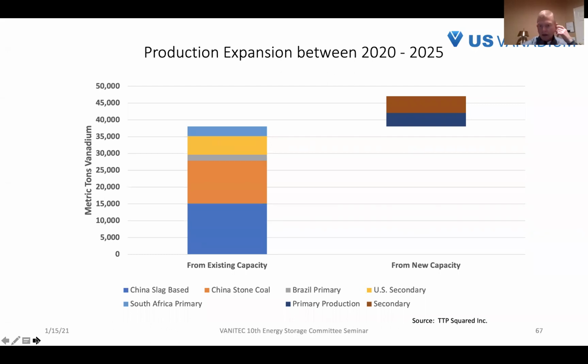And we also see a lot of secondary production, that is vanadium production from ashes and residues generated from either refining or burning vanadium-bearing oils. We're going to see a surge in the availability of these materials as a result of a change in the International Maritime Organization specifications for sulfur in bunker fuel. Previously, bunker fuel was simply the bottoms coming out of the refinery, blended together and burned in seagoing vessels. Today, the new standard requires sulfur levels to be about an order of magnitude below what you typically see. And what that means is these heavy bottoms are going to have to go over a catalyst and be cracked to remove that sulfur before this material can be burned as bunker fuel.